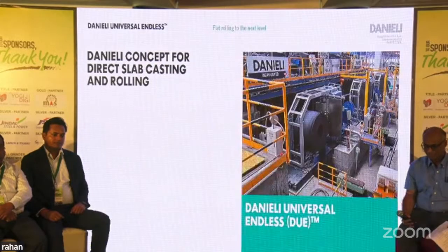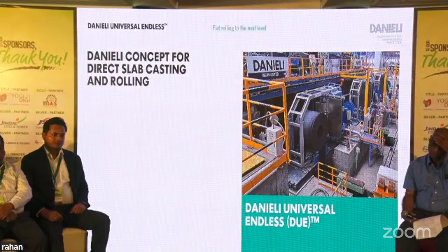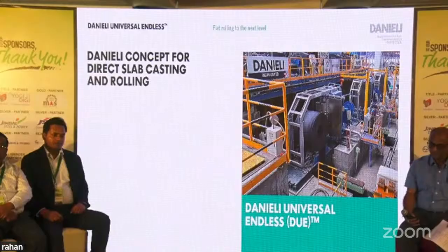So there we come to the Danieli concept for direct slab casting and rolling. Previously, there was a concept of thin slab casting and rolling because the slab that was cast was around 40 mm, 50 mm, 60 mm, 70 mm, but no more. And we have changed this by calling it direct slab casting and rolling because with Danieli technology, we have proven slab thicknesses up to 150 and 160 mm. It's no more thin. It's, you can say, a substantial amount of thickness.